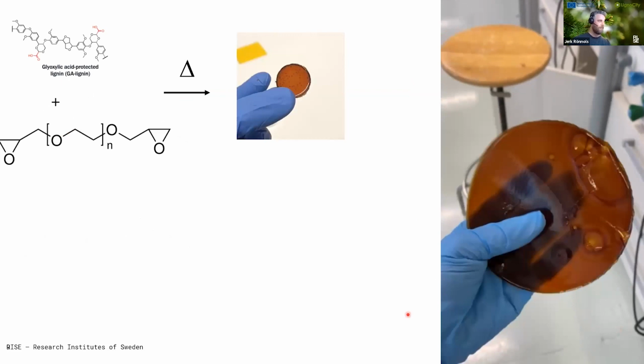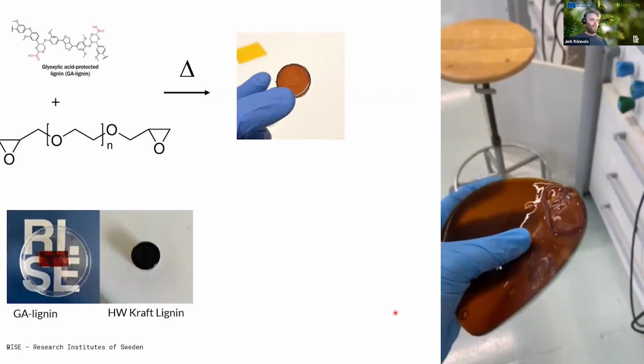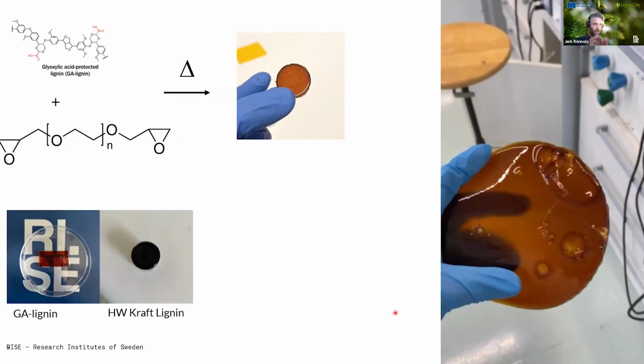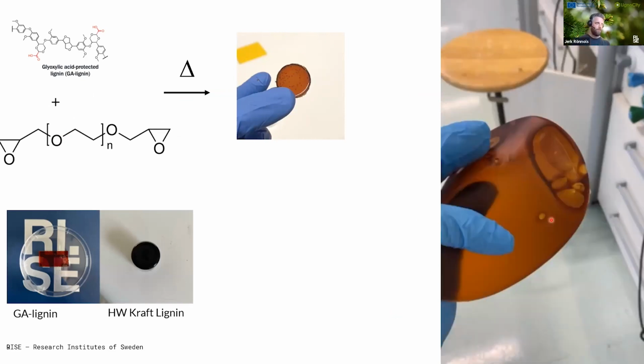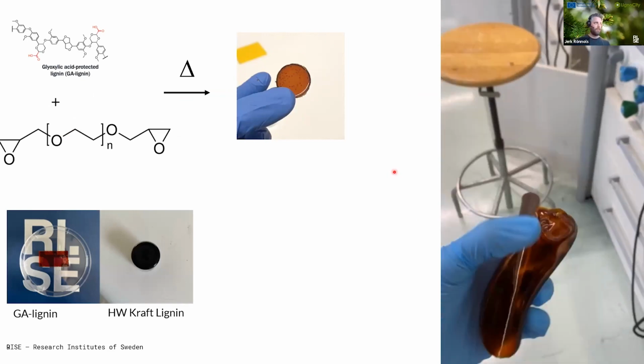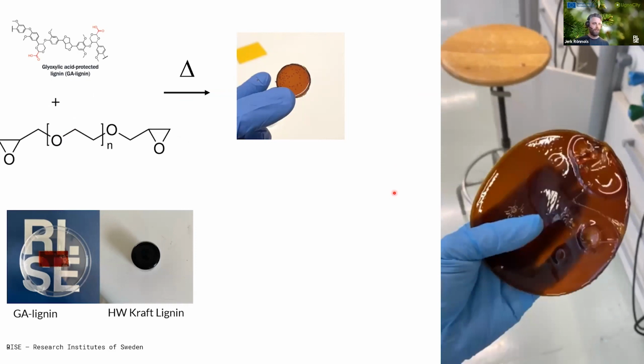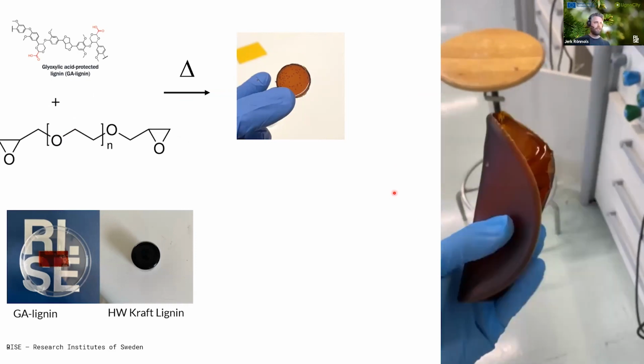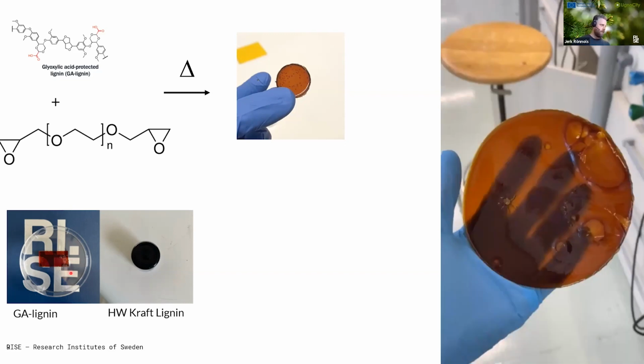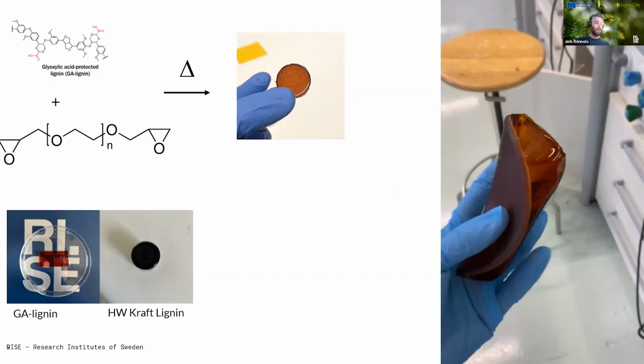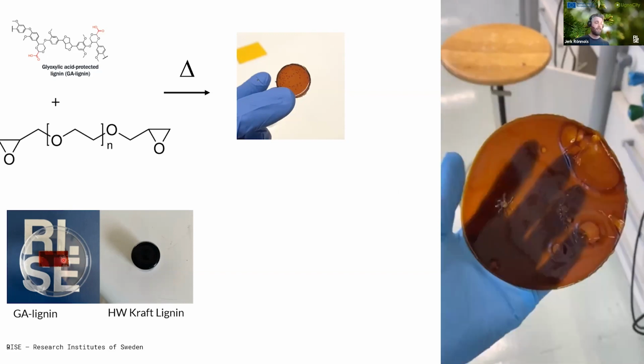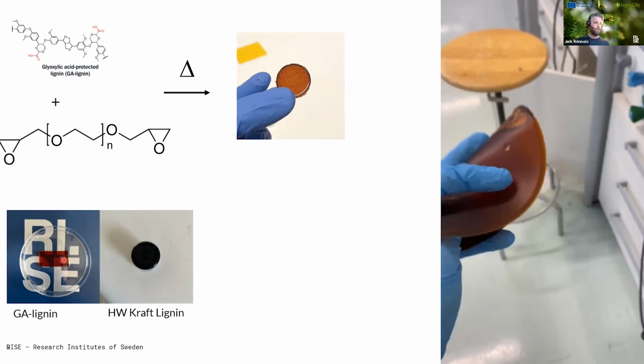And depending on how we produce it, we can get it in some different qualities. So this larger one also has some air bubbles in it, as you can see. These were made in a solvent-free way. So just mixing this highly viscous liquid with the powder, it's a bit tricky to get it to disperse properly. This one here, which you see overlaying the RISE logotype, is from a solution-based system where we have dissolved everything in dioxane, which gives a much smoother end result.